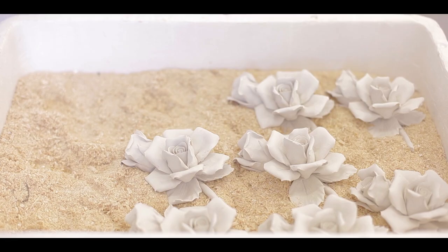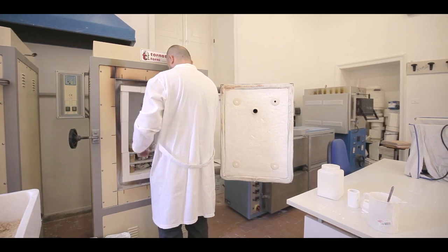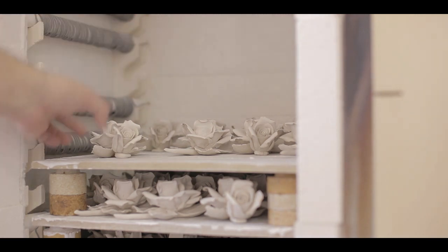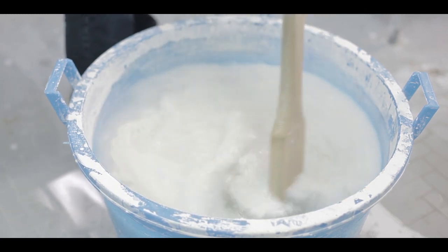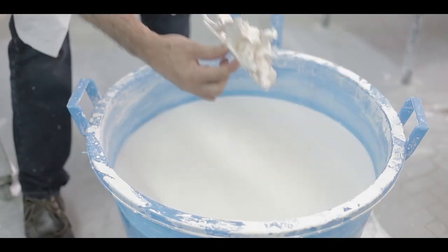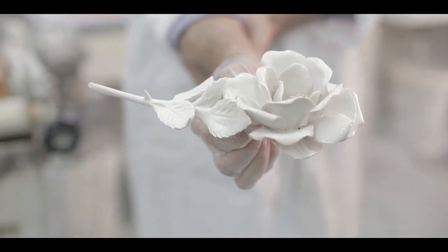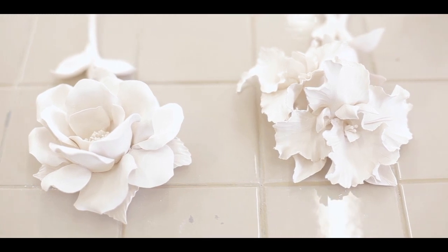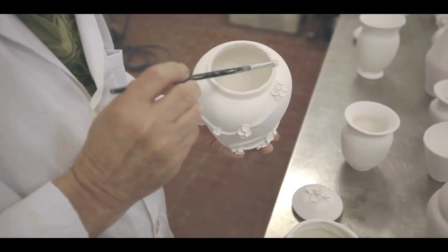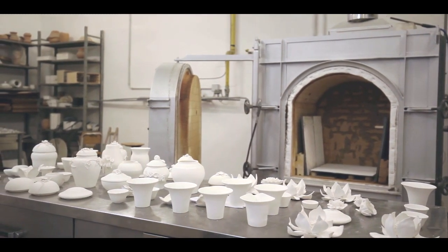Porcelain is normally divided into soft porcelain and hard porcelain. Porcelain for artistic use is essentially a soft porcelain, and soft porcelain itself is normally divided into biscuit and glazed porcelain. The substantial difference is that biscuit is porcelain without any glassy coating, while glazed porcelain is coated with what is called in ceramic jargon 'coperta per porcellana' — the porcelain cover glaze. This cover glaze is essentially a glass that coats the piece and is made of the same components as the porcelain body — kaolin, feldspar, and quartz — only with the vitreous flux component predominating over the kaolin.